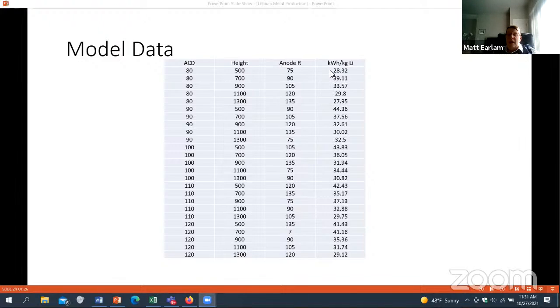So to give you some examples, magnesium runs about 13 kilowatt hours per kilogram of magnesium, and aluminum even less. So you can see, because the decomposition potential is so high in lithium, that it really affects the kilowatt hours per kilogram of lithium metal made. And in some of the examples where they really increased the gap, you can see they got to some pretty high energy consumption numbers.